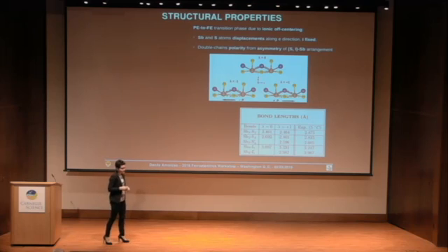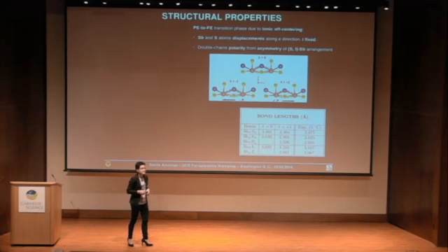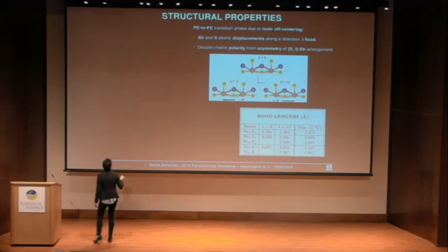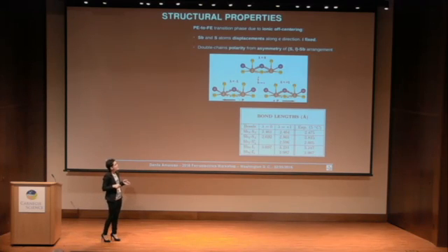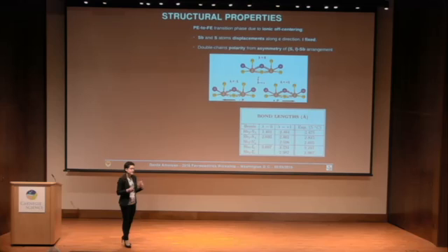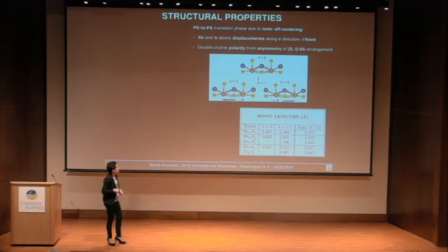From a structural point of view, the phase transition is due to a relevant motion of the antimony and sulfur atoms that move along the c direction, whereas the iodine is fixed. This displacement causes an asymmetry in the arrangement of the antimony-iodine and antimony-sulfur bonds that produces the polarity of the crystal.